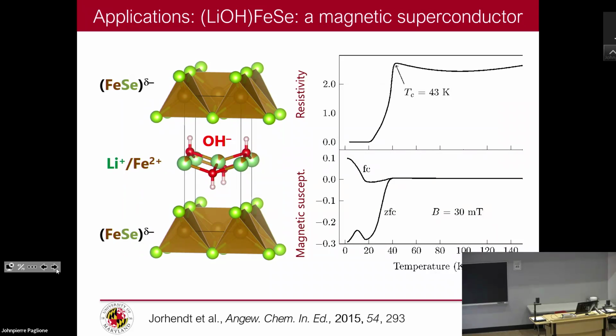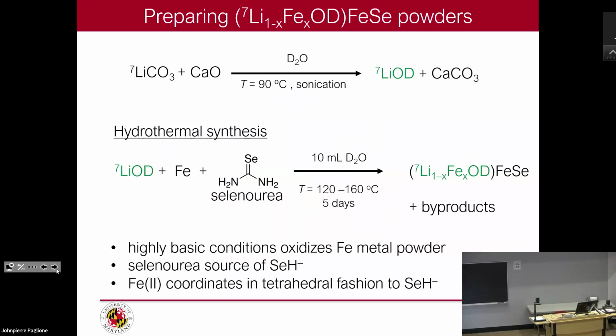All right, one of the interesting systems that you can make under hydrothermal conditions is this iron selenide intercalated by lithium hydroxide. The lithium gets replaced a little bit by iron 2+, so this layer becomes slightly positively charged, and that electron goes into the iron selenide, and it becomes a superconductor up to 43 Kelvin. And what's interesting about this is that if you get enough iron, this layer can also become ferrimagnetic, and so you can make something like a magnetic superconductor. That was one of the reasons we started getting involved in this.